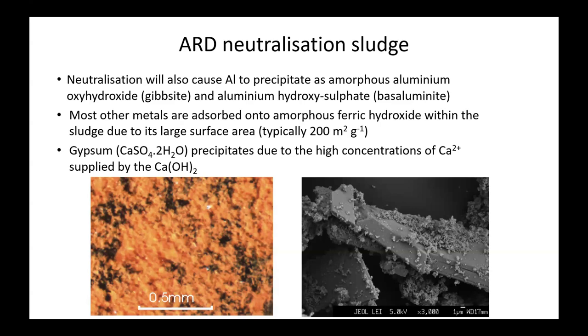Now, the other metals in solution, like the copper and zinc and the lead and the cadmium, mostly get adsorbed onto the amorphous ferric hydroxide. So ferric hydroxide is a fabulous material for scavenging metals and arsenic, just in passing. It has a really large surface area per gram, like 200 square meters per gram. It's big, so it can absorb a lot of metals.